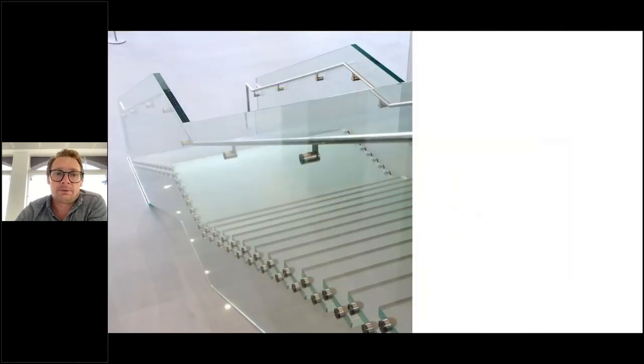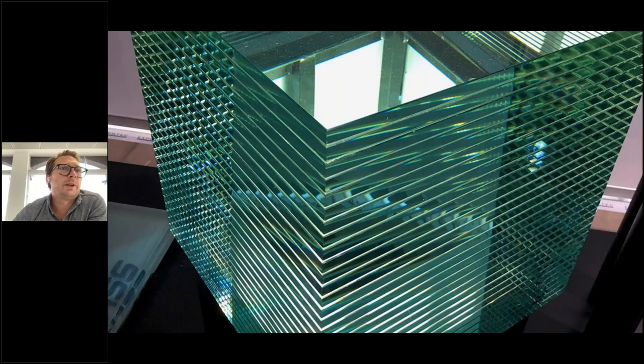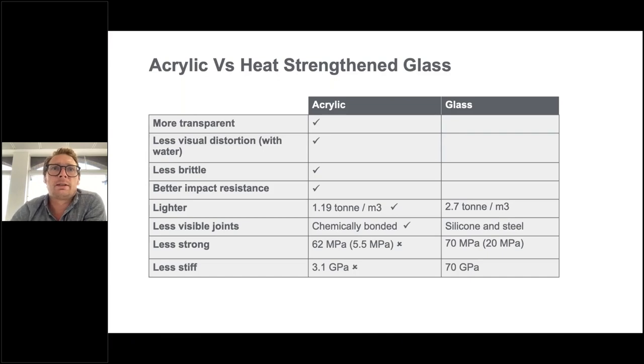Now, while we haven't shied away from those sorts of things in the past, we've built plenty of long structures with holes in, spanning horizontally and carrying vertical load. The holes were causing such a magnification that we needed to continue to add more and more glass. And while we can, that doesn't always make it practical. As can be seen here, I think this is a laminated glass by Seele. I won't leave you to count the leaves, but it's rather impressive, but completely impractical. So we turn to acrylic, which is lighter, but less strong and less stiff.